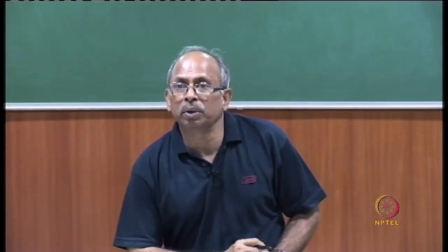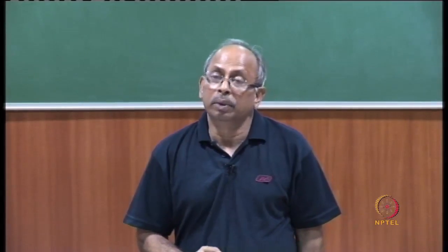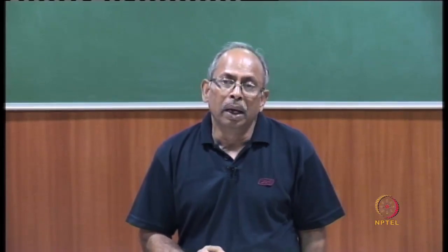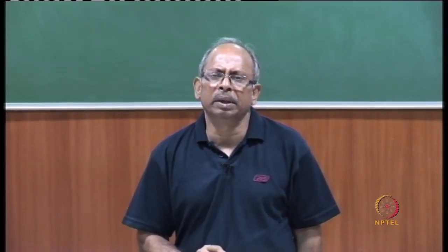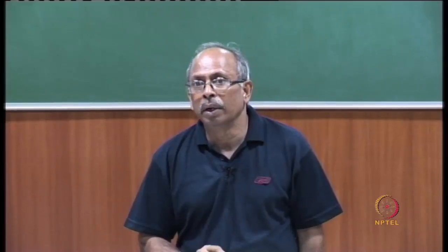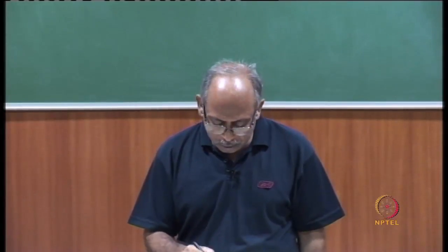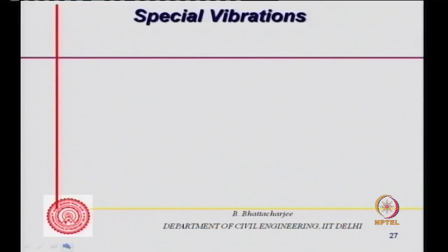Vacuum vibration is accomplished by applying vacuum to the surface of fresh concrete. Cement paste is densified by removal of air from the surface and water from a certain depth. Now this is applied for vacuum dewatered concrete floorings, with high abrasion resistance, like warehouse flooring or industrial flooring. So this is done where you are likely to have a lot of abrasion. Basically, water is removed. This water is used for placing the concrete, but it is removed. So the water cement ratio is low and you get relatively strong concrete.